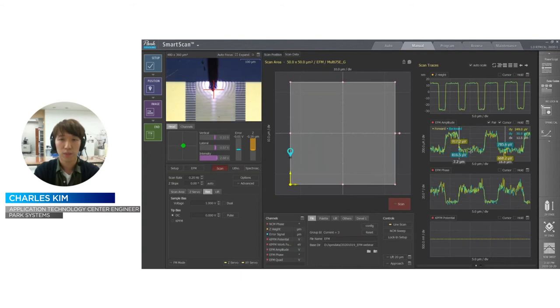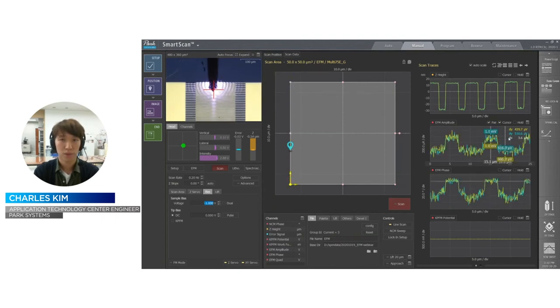So for example, when I apply 1 volt, the EFM amplitude signal has this kind of value, 1.5 millivolt and 800 microvolt. So if I change it to minus 1 volt, it's a little bit decreased, but still this electrode and this electrode have higher electrostatic force. But